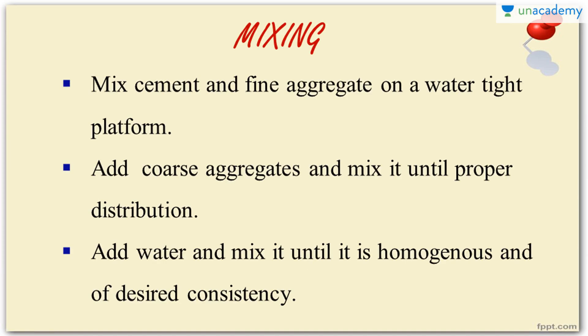Mixing must be done in a systematic manner. First, mix the cement and fine aggregate thoroughly until a homogeneous grayish-colored mixture is formed. Then add the coarse aggregates and mix until they are completely distributed. Finally, add the design water and mix until a homogeneous mix of desired consistency is achieved.